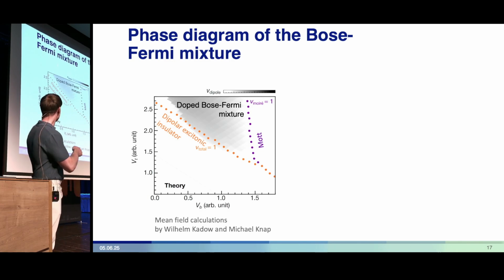You can see that in this wedge-shaped region in the electrostatic phase diagram, you have this doped Bose-Fermi mixture where we have dipoles. It's bounded on the left by the pure dipolar excitonic insulator, the charge balance case, and it's bounded on the right by the Mott insulator residing in the heterobilayer.